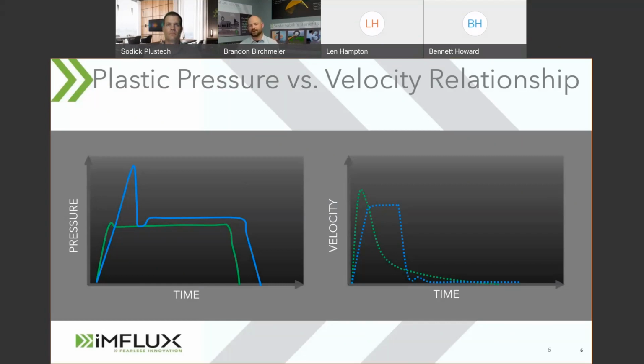With the influx process, that velocity will always be managed by the part and material. So there is a minimum pressure threshold here. I think that's important to recognize. There is a minimum amount of pressure I need to fill that part out. Once we find that, and you get the parabolic relationship you're looking at here, that flow front velocity is going to vary very much like you're seeing in that curve. We're going to have high injection speeds at the beginning. Once we get up to that pressure set point, we're going to start slowing down parabolically, just like you see in this curve here.